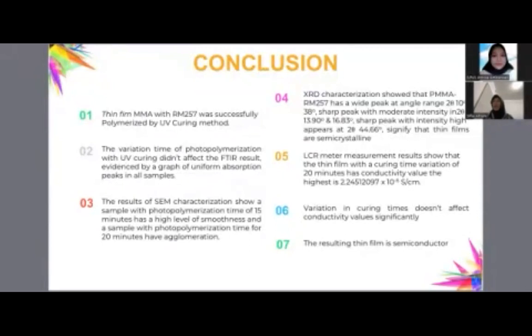XRD characterization shows that PMMA and RM257 have a wide peak at angle range 10 to 38, with subpeaks of small intensity at 13.90 and 16.83. A subpeak with high intensity appears at 44.66, which signifies that the thin film is semi-crystalline.